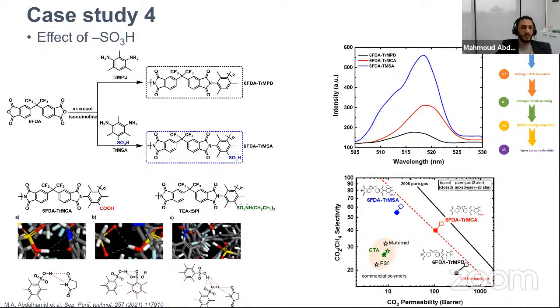Okay, so by doing simulations, we also found that there is a strong interaction resulting from the presence of SO3H as a hydrogen bonding source, where it can form hydrogen bonds with carbonyl and nitrogen within itself, like from different groups and different chains, and it can form a complex of hydrogen bonding with all of the atoms around.